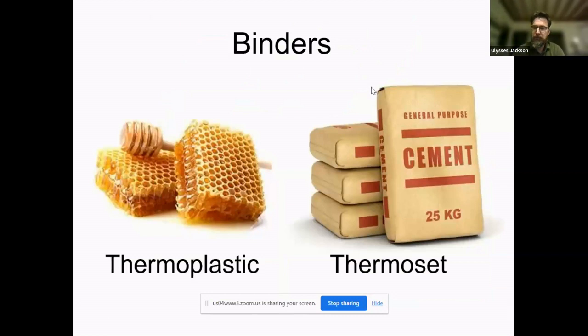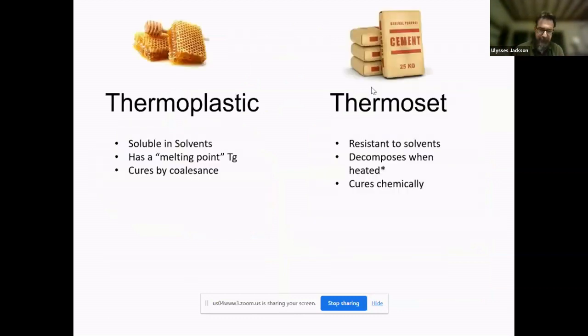Binders come in two main categories. There's lots of subcategories, but to keep it simple, you have thermoplastic and thermoset. A thermoplastic binder is soluble in solvents. It has a melting point called a Tg, or a glass transition temperature, and they cure generally by coalescence. Thermosets are resistant to solvent. They are kind of a one-way street. So if you heat them, instead of melting, they'll typically decompose, and they cure somehow chemically.